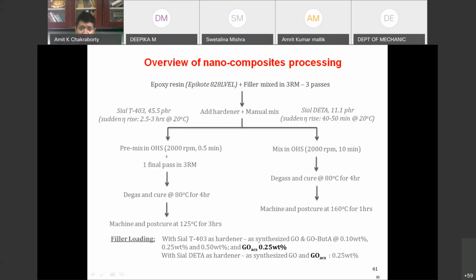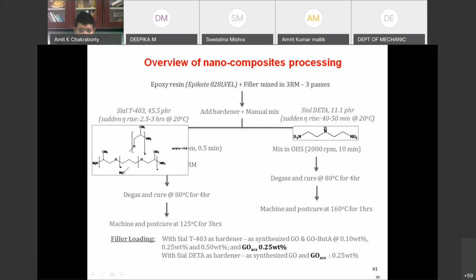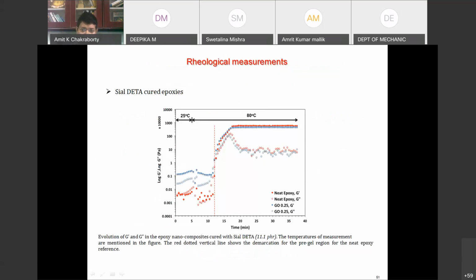We used two sets of hardeners, one hardener that cures very fast, one that cures very slow. And this is the data of G prime and G double prime, which are nothing but the storage modulus and the loss modulus. You can see that the values are at room temperature, up to 25 degrees Celsius. These blue values are essentially increased.